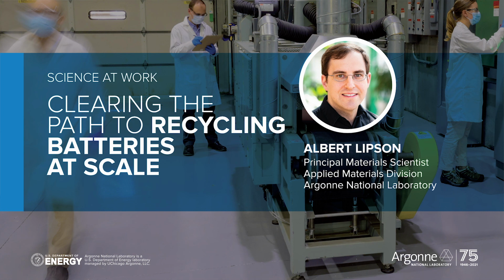So at this point, we have separated cathode and anode. Now we need to recover the cathode material. So one of the last steps we need to do is actually add lithium back into that cathode material, because during the cycling process, the cathode will lose lithium into the SEI that forms on the graphite material. The SEI is the solid electrolyte interphase. And from that, we're actually able to regenerate the cathode. So we do this by just heating it with some lithium hydroxide, and we get back a cathode material that actually performs quite well in cells.